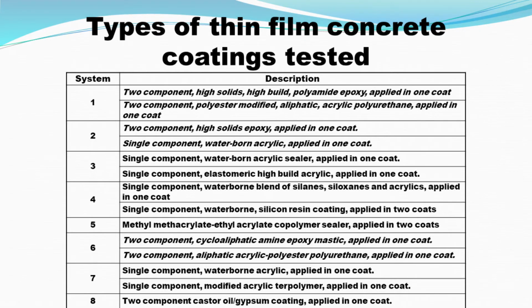System 5 was a methyl methacrylate-ethyl acrylate copolymer. System 6 was a cycloaliphatic amine epoxy with an acrylic polyester finish coat. System 7 was a waterborne acrylic and was a 2-coat acrylic system. And then 8 was a castor oil gypsum coating system.